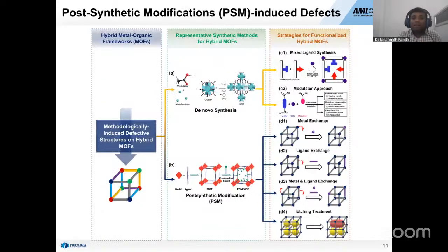Then again, I told you there are two types of methods, like the de novo synthesis method. When you synthesize the MOF, at that time you can change the temperature, pH, or different controls, and synthesize using a modulator. Another method is post-synthetic modification. After the one-step synthesis of the MOF, we can modify it, like change the ligand or change the metal, or use the etching method, which means you can etch, like wash with a low concentration acid. You can etch one metal. Etching means you can replace one metal, which can make the defect.